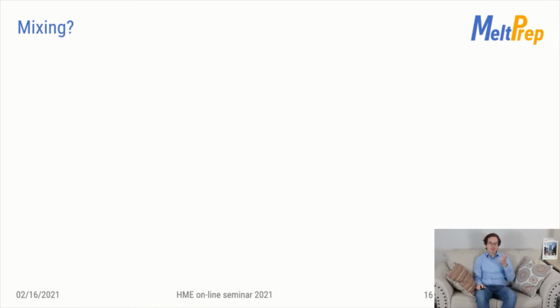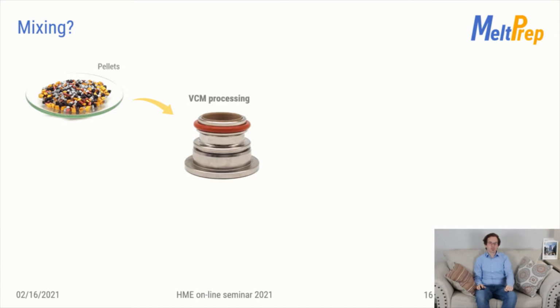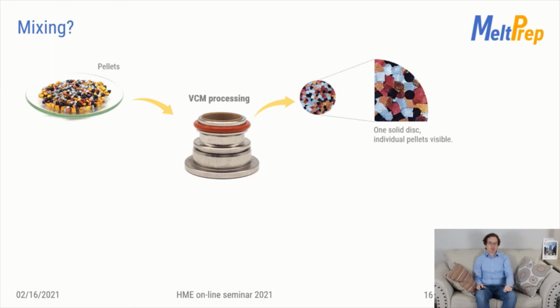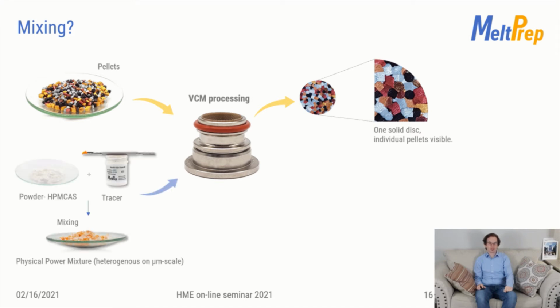If one puts multicolored pellets into the sample chamber and runs the VCM process, one will obtain a disc without any air inclusions. But you can clearly see the phase boundaries between the individual pellets. There are no shear forces and no macroscopic mixing. How can we obtain a homogeneous result then? By using powders instead of pellets to enable mixing via diffusion.